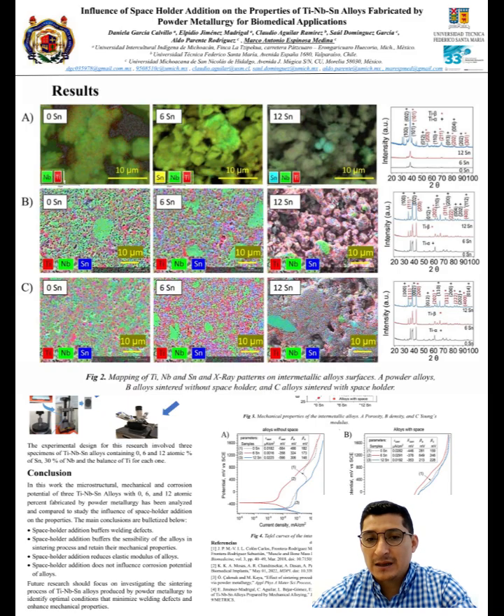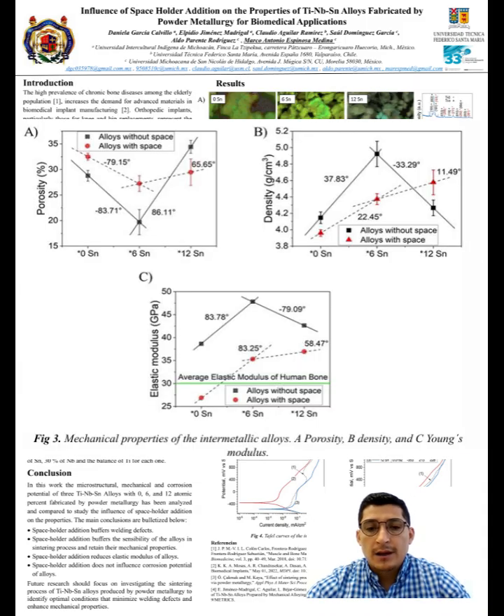In rows B and C, the characterization of the alloys sintered with spaceholder agent and without spaceholder agent are presented. This micrograph indicates some agglomerates of niobium and tin. Also, patterns for these alloys indicate the presence of two crystalline phases, beta and alpha titanium. In figure 3, the mechanical properties of the intermetallic alloys are presented. In graphic A, porosity, in graphic B, density, and in graphic C, the Young's modulus.